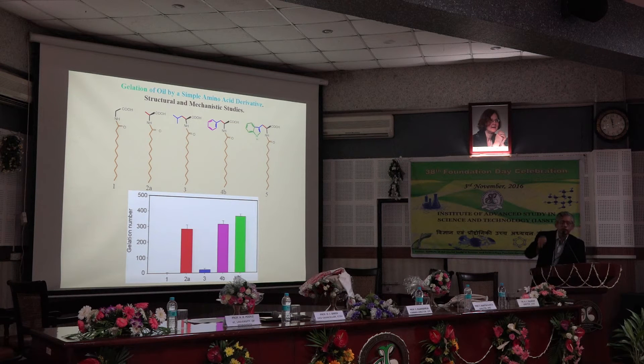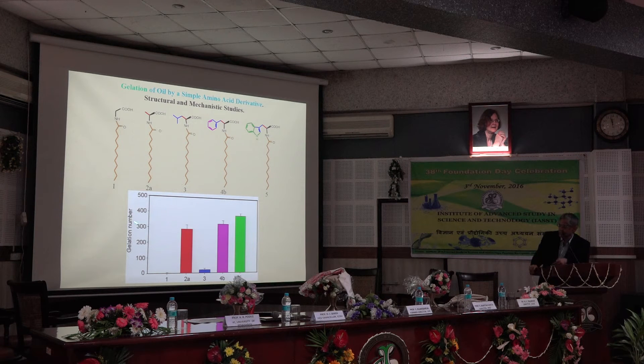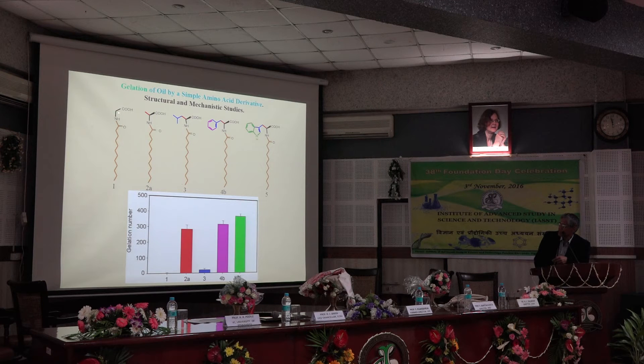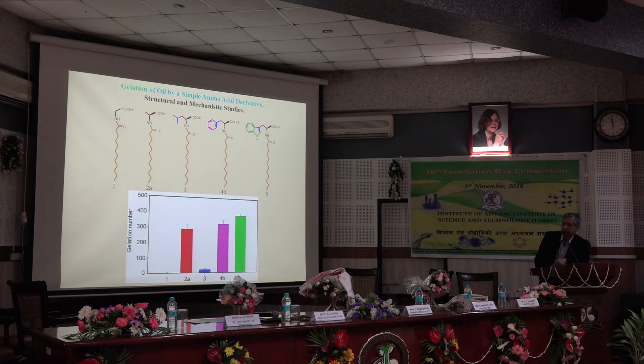But when it is alanine, it gelates. Just one methyl group makes all the difference. But when we add too many methyl groups — this is leucine — you can see nothing much happens. So there is some magic we can play just by playing around with the molecular structure.